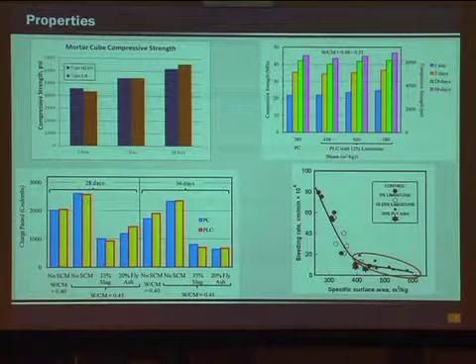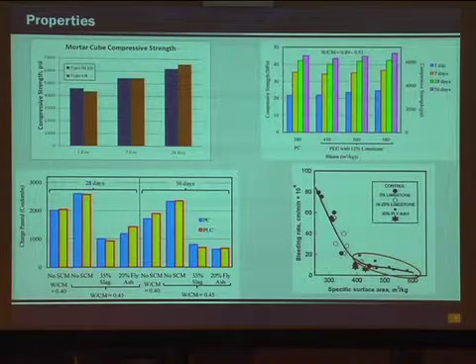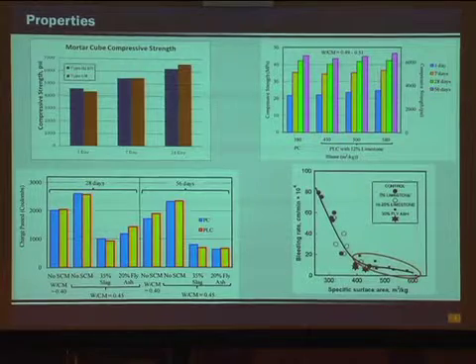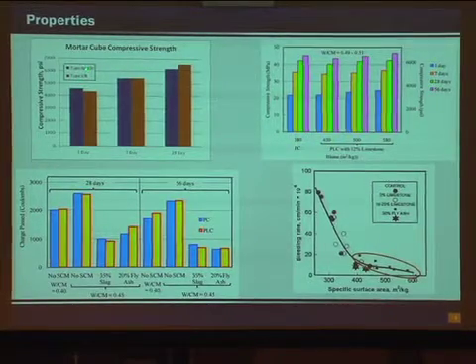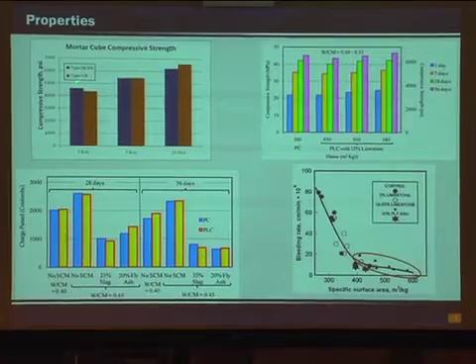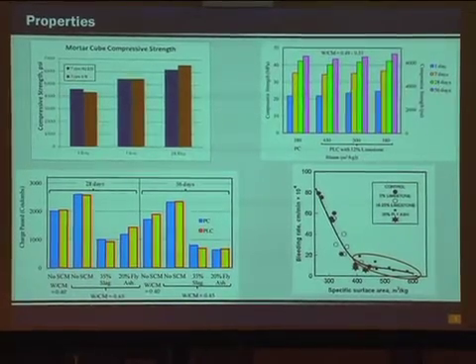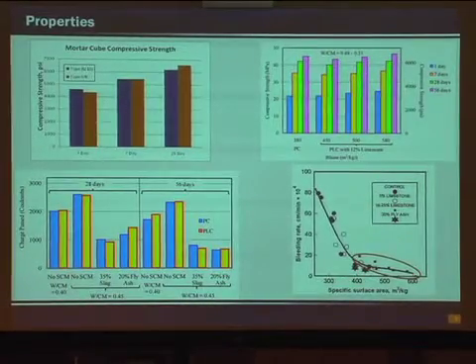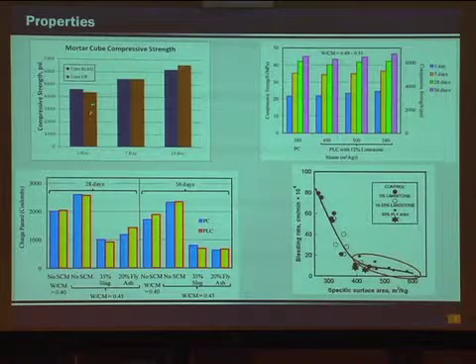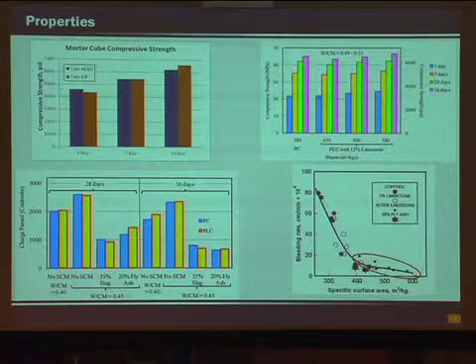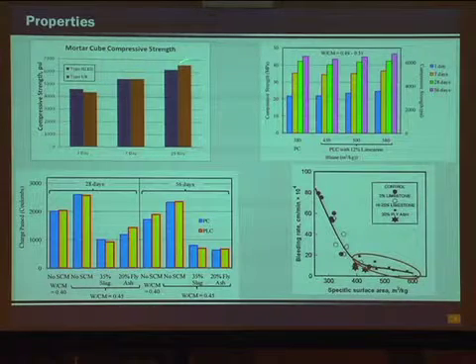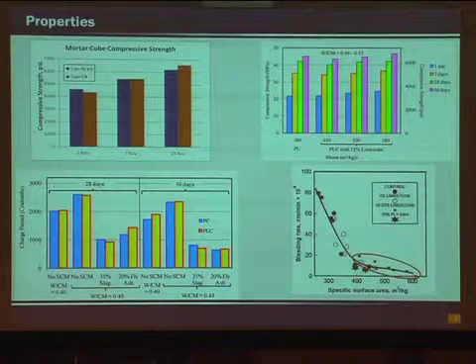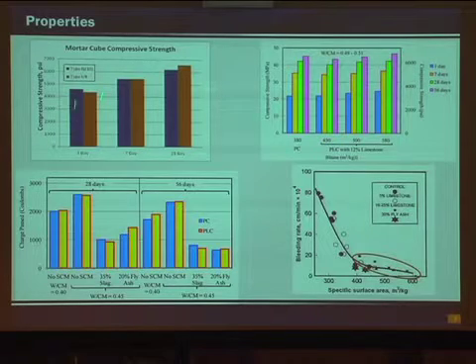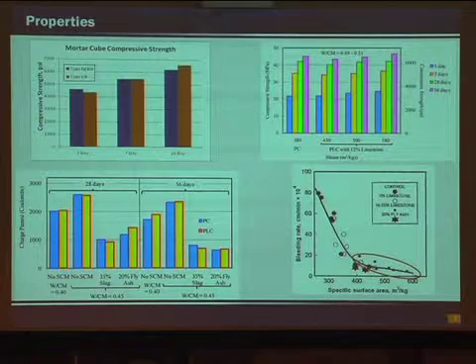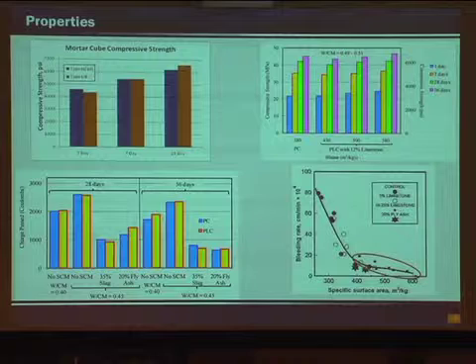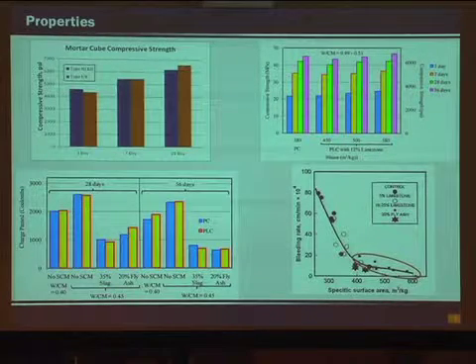Now some basic properties. The first one is compressive strength. This is a mortar cube. You can see the blue is a 1L with 10% limestone, and the brown or goldish color is your typical Type 1-2 cement. These are the same clinker, just with the limestone addition, and you can see there's not much difference in strength between the two cements. The reason is 1Ls are generally ground a little finer, so you get that equivalent strength of your base Type 1-2